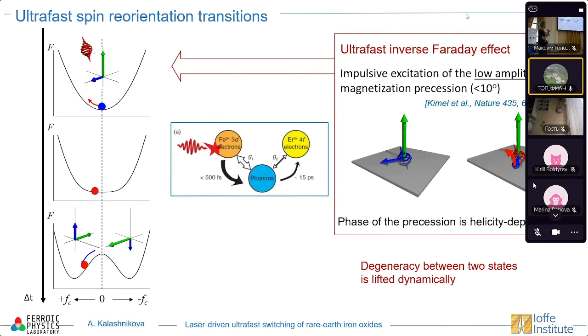If we change the polarization of the pump pulse, then the initial phase of this excited process changes. We know it from experiments, and therefore we'll end up in different minima. So basically, we use this bottleneck, and we combine our heating with the ultrafast inverse Faraday effect, with excitation of low amplitude precession, in order to control spin orientation transition. And basically, we kind of lift the degeneracy between these two states dynamically.